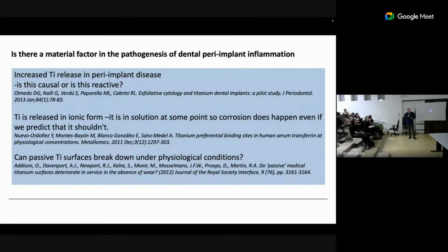But of course it points to the people who are turning around and saying, well, does titanium corrode in a dental situation? Well, let's look at the fundamentals of this first off. The titanium oxide surface layer should not spontaneously depassivate in physiological conditions until you get, at the earliest, up to about 68 degrees centigrade. So it is highly corrosion resistant and should remain highly corrosion resistant if we just think about a neutral physiological environment.